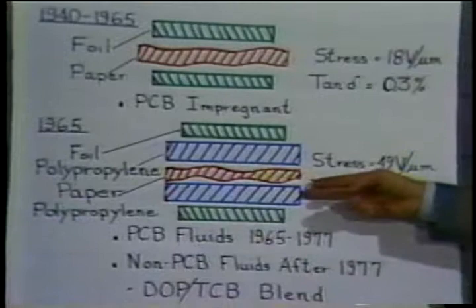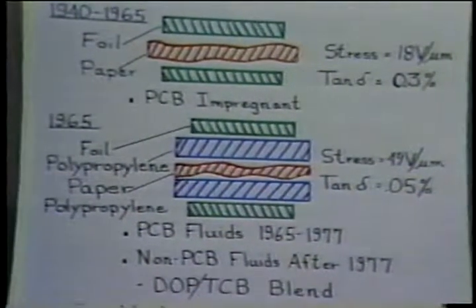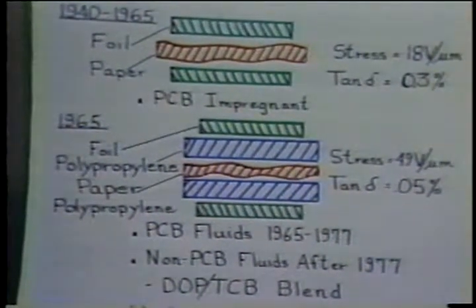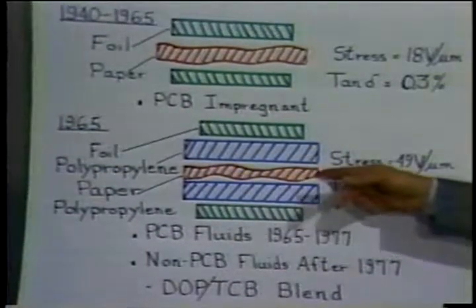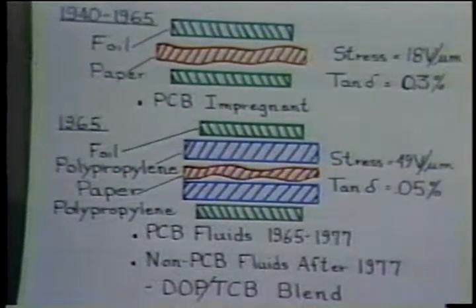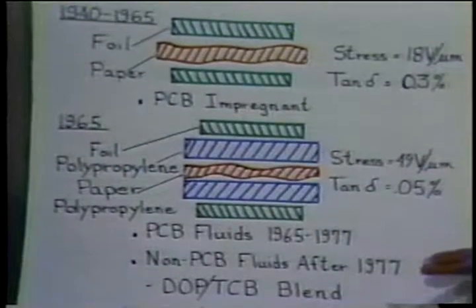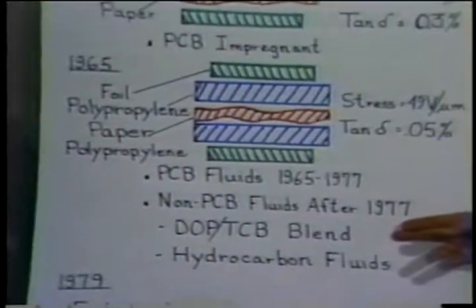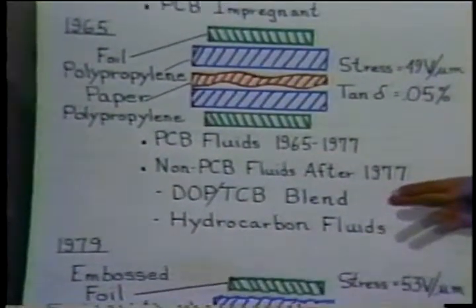The construction that was used was 2 sheets of polypropylene film with a sheet of paper in between them. The paper was used as a wick to pull the liquid into the capacitor roll. The fluids that were used after 1977 were either a blend of DOP, dioctyl phthalate, and trichlorobenzene, or a hydrocarbon fluid, such as phenylxylylethane or MIPB, monoisopropyl biphenyl.